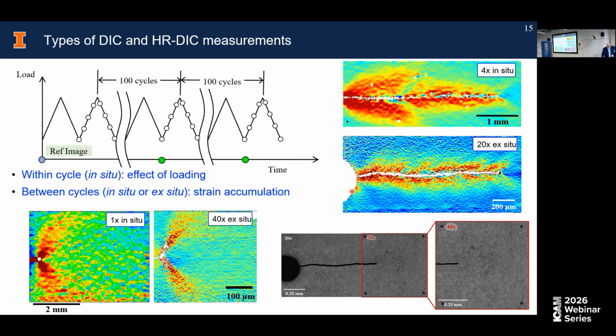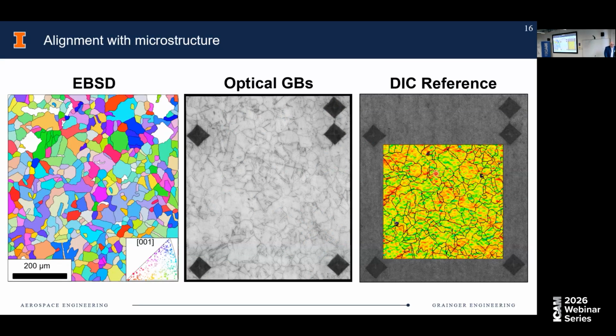Getting again what would be fatigue. It's not exactly the same, but this is actually in a different material. But what we would be getting would be a higher resolution of this plastic wake, or we could get a higher resolution of the development of the plastic zone in front of the crack tip. And you could do this at various magnifications. And then we could also eventually do a monotonic test to failure to get, let's say, fracture toughness or whatever else that we might want. So these are the types of measurements that we would do.